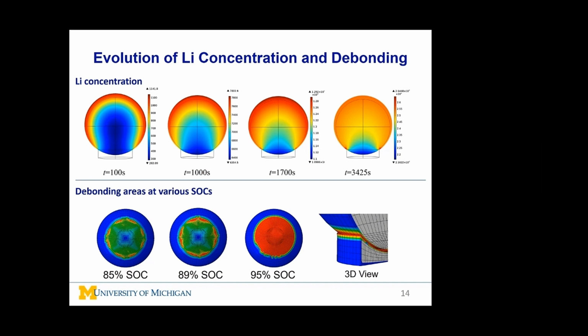Here we see the lithium-ion concentration distribution. Because the flux of lithium ions is blocked by the binder region, the concentration distribution is not spherically symmetric. With increased state of charge, more areas are debonded, shown in red.